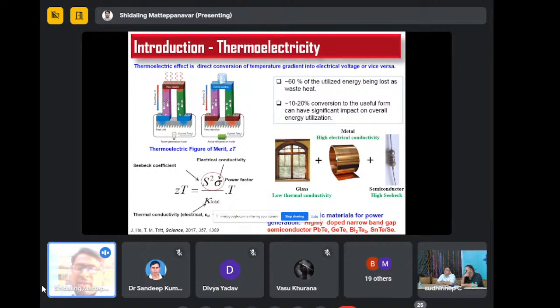These thermoelectric materials are evaluated on the basis of the figure of merit, ZT. Here I have mentioned the equation: ZT equals S squared sigma by kappa total, times temperature. Here S is the Seebeck coefficient, sigma is the electrical conductivity, and kappa is the total thermal conductivity. To have a better thermoelectric material, one should optimize all of these parameters.